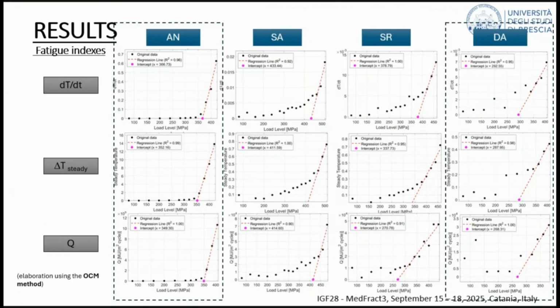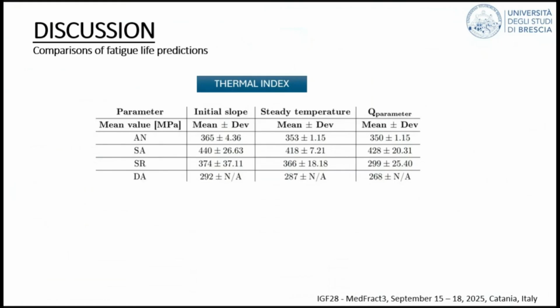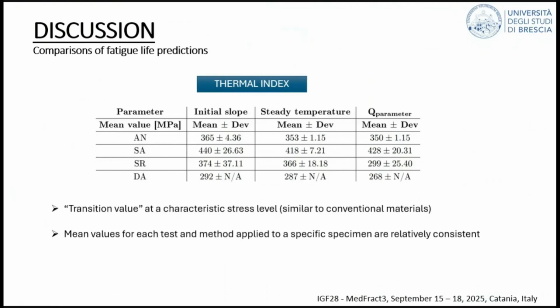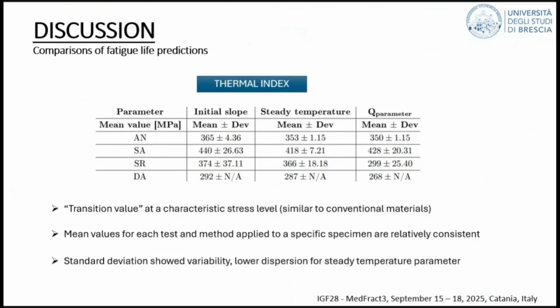Then you see three different types of index in this case, and I have summarized the results in this table. In this case, what we have found is that there were no significant differences between using the initial slope or the steady temperature or the Q parameter. So except, let's say, one case, which is the stress relief condition, basically, we get very consistent predictions. In all cases, we have this transition at a characteristic level, so it was possible to identify a fatigue limit. Maybe the only difference among the three indexes is that when we apply the steady temperature, the deviations, the standard deviations are more favorable.